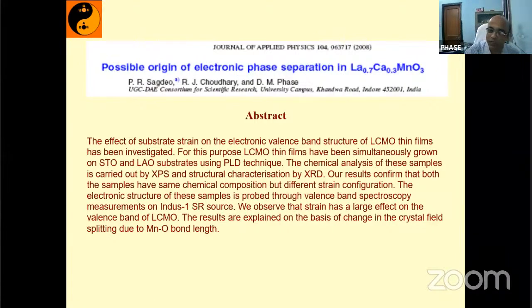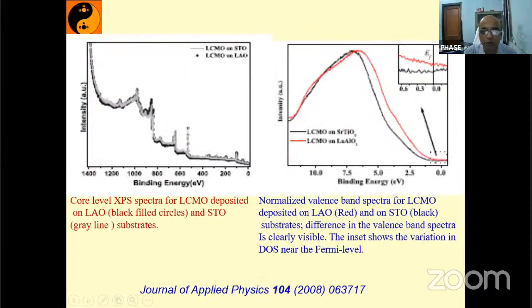But in thin film form, again there is a problem, which is which type of substrate is used. Because of the substrate also, one can get a change in the properties of the same material. If you use a different substrate, then the same lanthanum calcium manganite will show you different properties. So how can one check it? That is done in this paper using synchrotron-based photoelectron spectroscopy. This is the normal core level XPS spectra done at the laboratory.